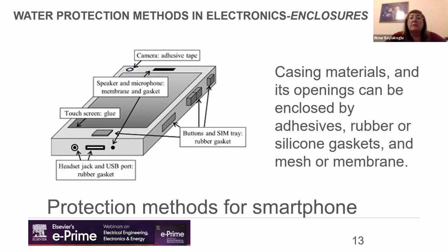And openings covered with hydrophobic materials, which naturally repel water, cause droplets to form. And these can be used to regulate pressure in non-hermetically sealed packages without allowing liquid water to enter. And rubber gaskets and adhesives are used to seal the openings on product housings. These can be degraded by some environmental loads like salty moisture, temperature fluctuations, and solar radiation. So even during usage, cracks and other defects may form and will contribute to more moisture ingress over time.